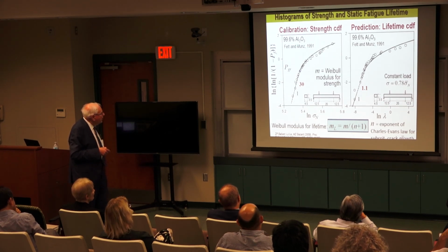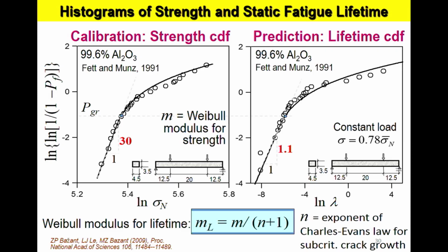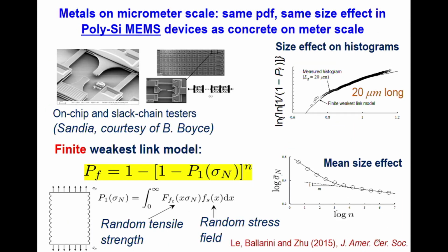There are not many tests, but Fett and Munz tested on the same material, aluminum oxide, short time strengths, slope 1 over 30, will be very small size effect. So 30 to 1, very small size effect. Here the size effect would be 1 over 1.1, extremely large. Both are fitted with the same law, and this is verified by this analysis.